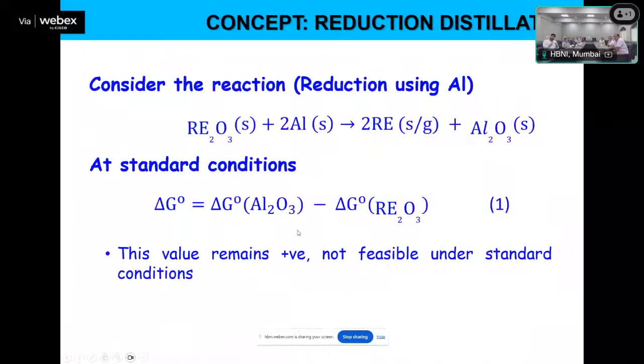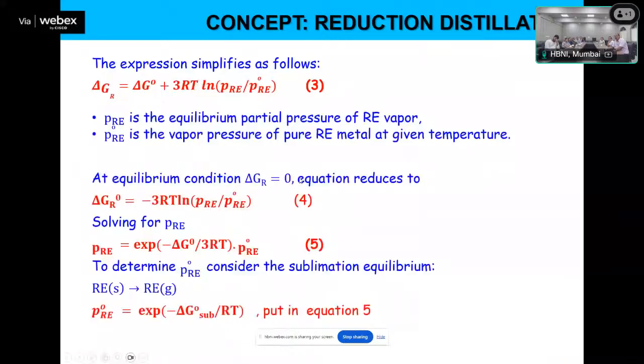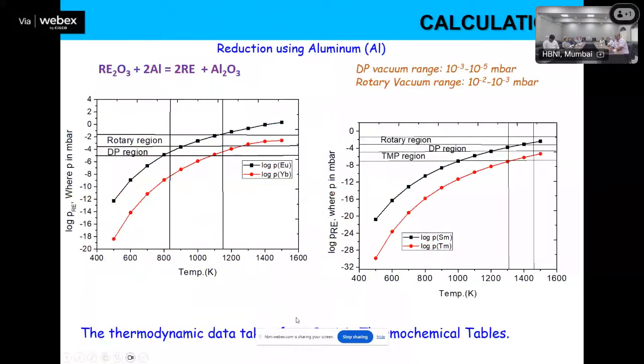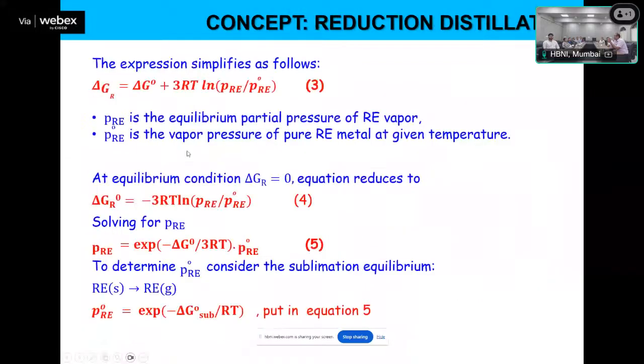But at non-standard condition, delta G is equal to delta G naught plus RT ln K, and this K was written in terms of activity, and finally activity is written in terms of partial pressure. At equilibrium, when delta G is equal to 0, this equation reduces to this, and this PRE was calculated. For this reaction, PRE comes to 10 to the power minus 3 millibar, meaning at 10 to the power minus 3 millibar delta G is equal to 0, it is in equilibrium. So once you apply a vacuum better than 10 to the power minus 3, this delta G will be more negative. This is the funda which we applied: high temperature and using the vacuum.